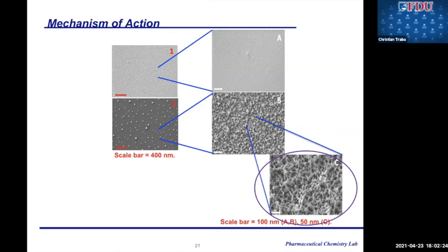In addition, the high stability of the anti-infection surfaces from our previous slide can therefore be explained by the multiple attachment sites between the polymer brushes and the silver nanoparticles, resulting in these cross-linked nanocoatings. When immobilized surfaces were further examined, multi-layer cross-linked silver nanoparticle surfaces were constructed under the above experimental conditions. Silver nanoparticles were uniformly distributed throughout the surface and were bound in between the polymer brushes in a multi-layer fashion, and there was minimal silver nanoparticle aggregation.